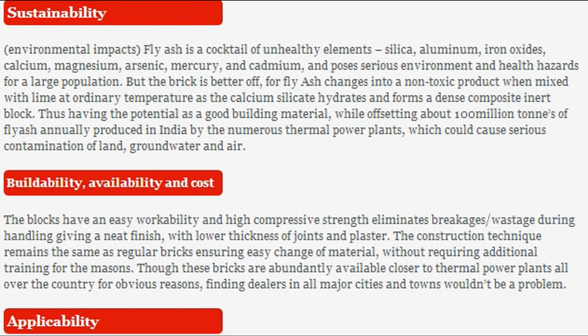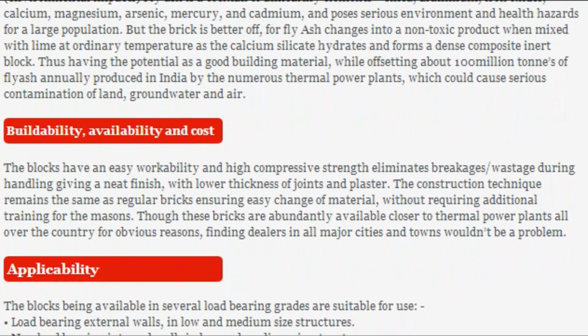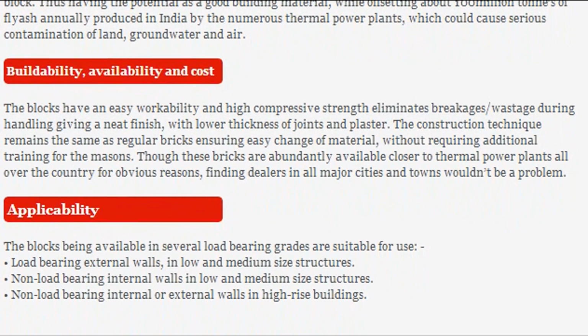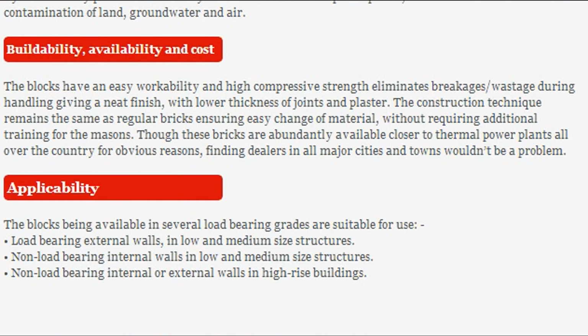Sustainability, environmental impacts: fly ash is a cocktail of unhealthy elements: silica, aluminium, iron oxides, calcium, magnesium, arsenic, mercury and cadmium, and poses serious environment and health hazards for a large population. But the brick is better off, for fly ash changes into a non-toxic product when mixed with lime at ordinary temperature, as the calcium silicate hydrates and forms a dense composite inert block, thus having the potential as a good building material, while offsetting about 100 million tons of fly ash annually produced in India by the numerous thermal power plants, which could cause serious contamination of land, groundwater and air.